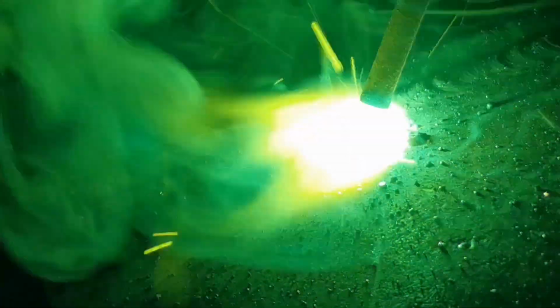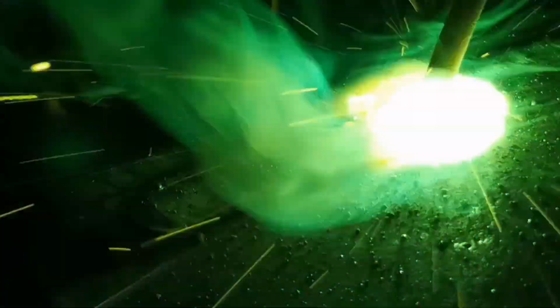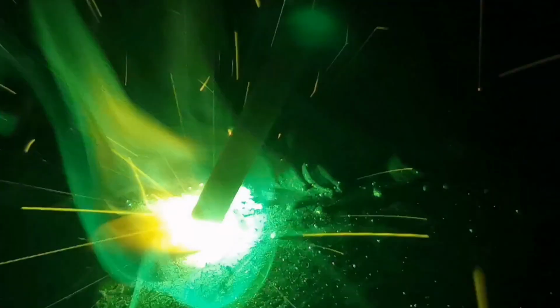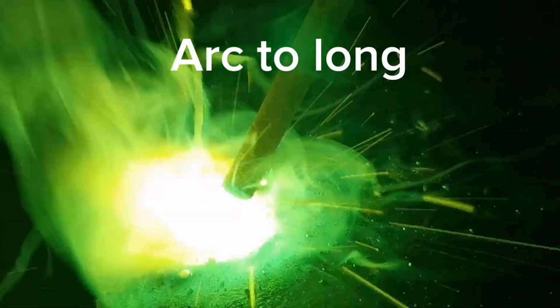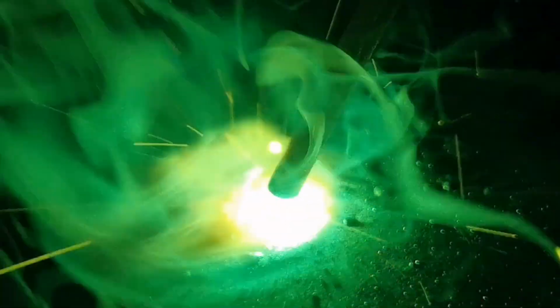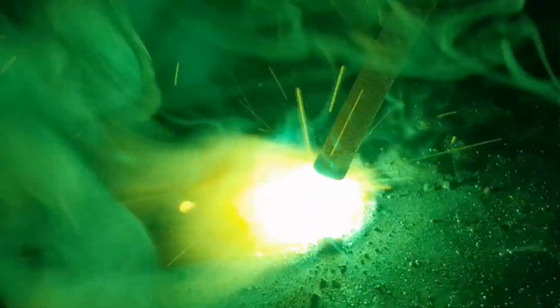So here you have it where the arc length is too long. We're probably 4 or 5 mil away from where we should be. You can see the welding rod cuts out all the time, so it won't keep a proper arc with the metal. So what happens then is you get an awful lot of spatter. The metal actually heats up an awful lot more, and you just get an all-round bad weld. Lots of impurities, probably lots of porosity, and just a very poor weld.